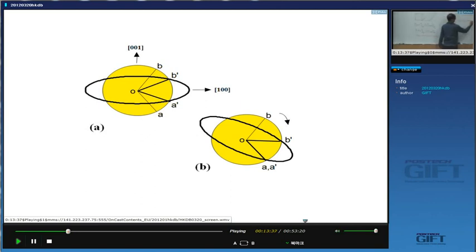So the Bain strain is only one part of the deformation. The other part is the rotation, which generates this invariant line. But there is no rotation which will give me two invariant lines, because we need two invariant lines to define an invariant plane. This line has gone further out of coincidence by applying the rigid body rotation. So there's still an inconsistency with the shape deformation which we observe, which is an invariant plane strain. Yeah? Everyone okay so far?